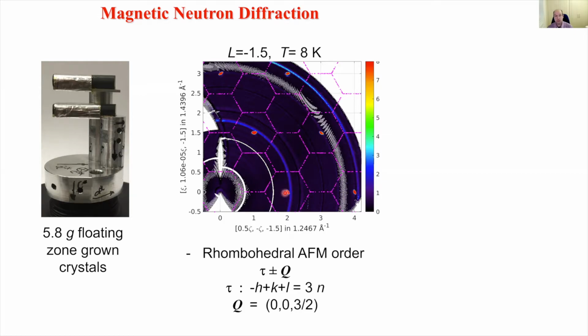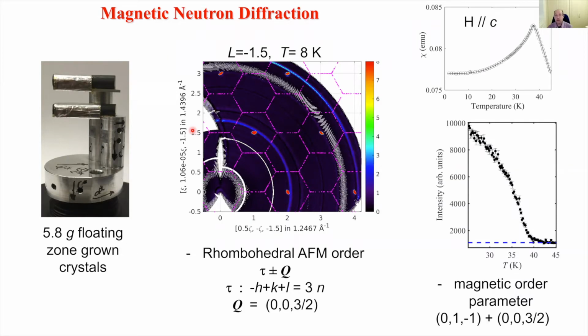The fact that one occurs every 3 zones is associated with the certain stacking that occurs between the layers. And if we sit at one of these positions and measure the intensity as a function of temperature, that naturally goes to 0 at the transition temperature through a nice order parameter. And this coincides also with an anomaly in the susceptibility at similar temperature to what's been seen in other studies as well. So that sort of confirms the stoichiometry of our sample and the high purity.